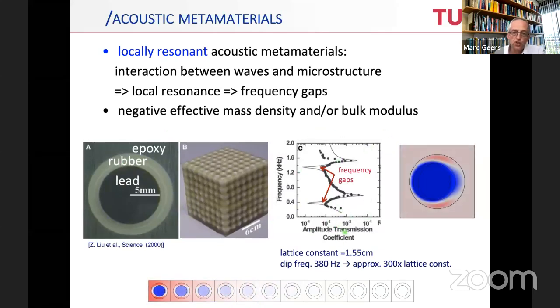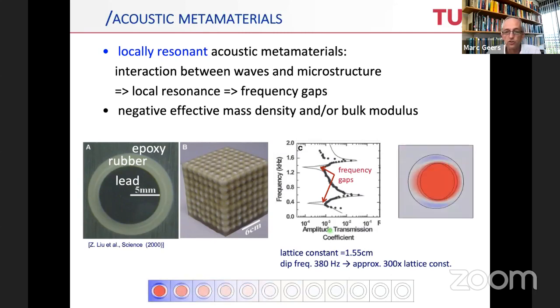And this is a transmission plot where you can clearly see an enormous decrease in the transmission coefficient at particular frequencies. And of course, these frequencies correspond with the eigenfrequencies, the vibrations of the particles that are in a local resonance state. The result thereof is that you enter an evanescent wave in the band gap. That's typically shown here at the bottom. I hope you can see a little bit of the movies where the wave enters on the left, but is unable to propagate to the right.